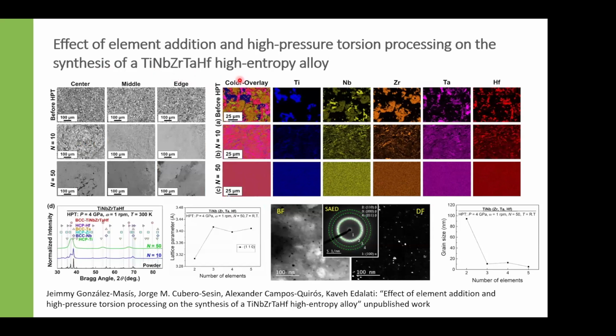We also tried high entropy alloys like titanium-based: titanium, niobium, zirconium, tantalum, hafnium. And the story is more or less the same, with the merit that these are 5 elements that are hard to mix usually, and the HPT process can mix them. After 50 turns, we have a very nice homogeneous elemental distribution,